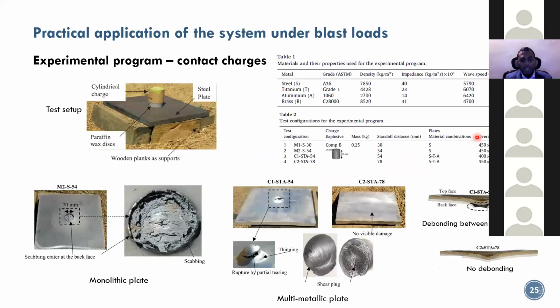And then we tested that for two kinds of charges. One was for contact charges. This is where the charge source is almost in touch with the material. So we first tested a steel plate, that's the reference one, and then we tested a new plate, the multi-material system. So when we had a steel plate at the back surface, we saw scabbing. Now I explained what scabbing is earlier. This is where because of tensile failures, material can get ejected out of the system at the back face. So we saw that there's scabbing if there was only steel, that's the monolithic plate.